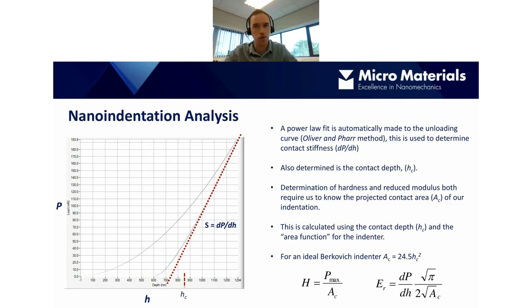First of all, in terms of these equations, load is denoted as P, capital P, and the depth is h. The most common model used for the analysis of nanoindentation data is called the Oliver and Pharr method, which is described here very briefly, of course. First, a power law fit is made to the unloading curve, and this is used to determine the contact stiffness, this term here. Also determined from this is the contact depth, which is hc.